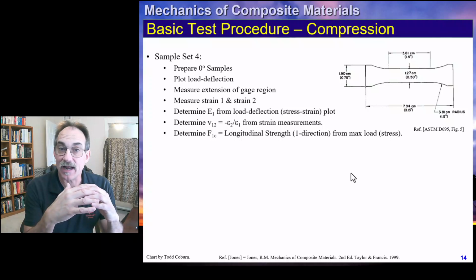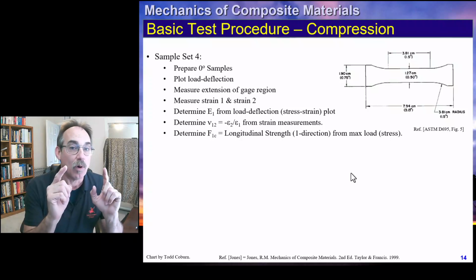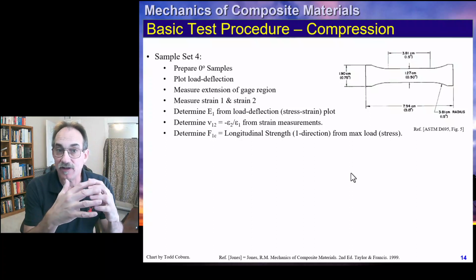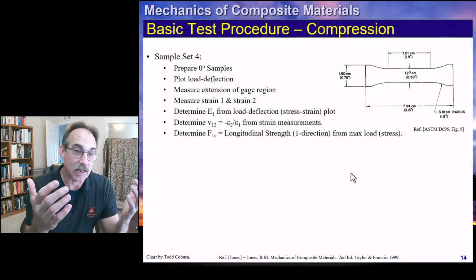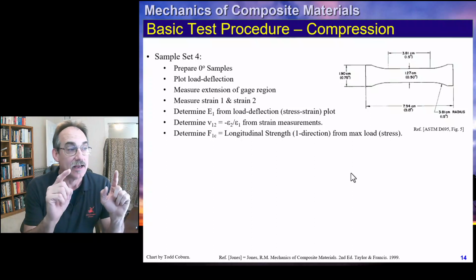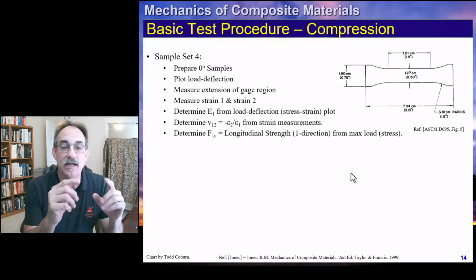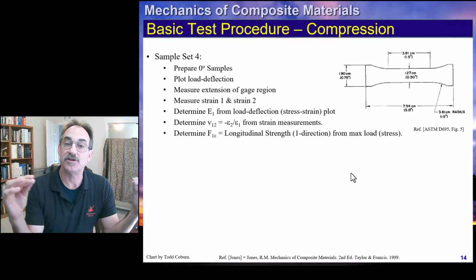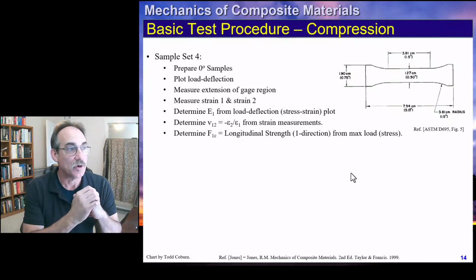This will pick that up. What we want to make sure it doesn't do is go into an Euler buckling kind of failure, because that we can do analytically, or we want to make a longer sample to evaluate that. If we're trying to get F1C, we need this to be short enough so we are picking up those stability failures that are within the composite, but not the ones that are a function of our geometry so much.